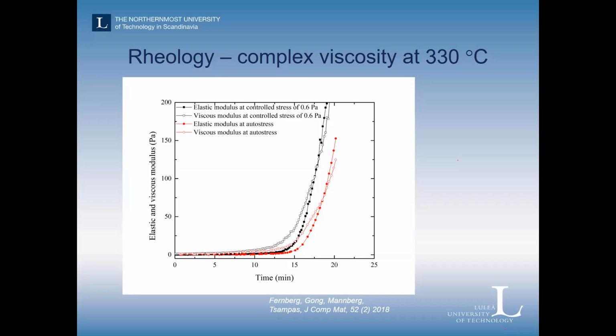And traditionally, the time to gelation is determined in this type of rheology setup when the elastic and the viscous part intersect, so when they cross each other, which is an indication of gelation. In this case, we can see that at 330 we don't have much time, but we have around 15, 20 minutes in order to fill the mold, which is quite a short time, but still something to work with.